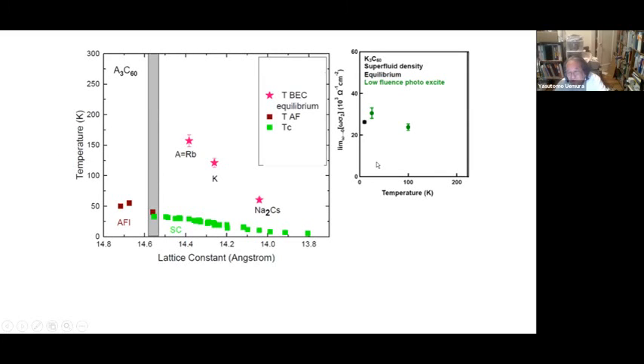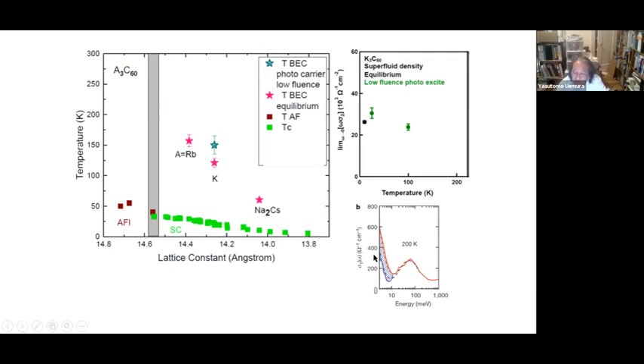And Andrea measured the transient superfluid density, and it has a little bit more spectral weight than the equilibrium spectral weight. So for example, for potassium 3C60, from this little bit more spectral weight, we would expect the hypothetical Bose-Einstein condensation to take place at this temperature. And you can compare with the real onset temperature. It is not quite easy to estimate, but something like this region would be approximately right for the onset temperature. And so in this way, we can say that this phenomenon has an onset temperature which is consistent with that predicted from this argument of the hypothetical Bose-Einstein condensation point.